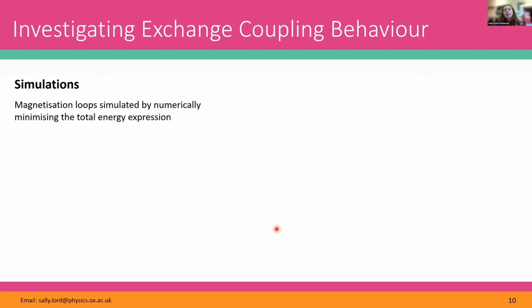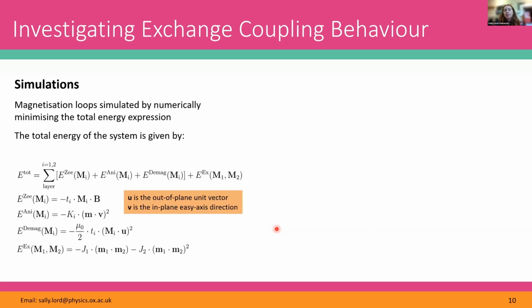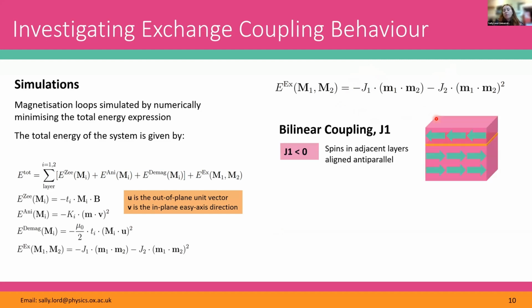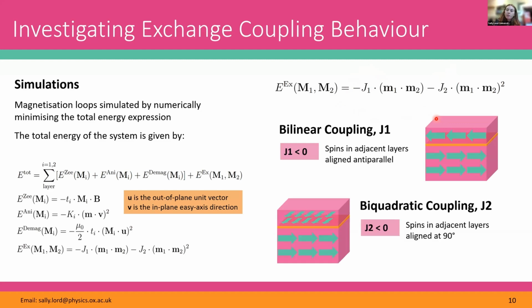So we simulated the magnetization loops by numerically minimizing the total energy expression. But in doing this, what we were really interested in was the exchange energy term, which is governed by these two constants, J1 and J2. J1 is the bilinear coupling constant, and J2 is the biquadratic coupling constant. And what we were really interested in working out was which type of exchange coupling is dominant in the system. Are we seeing more bilinear coupling or more biquadratic coupling?